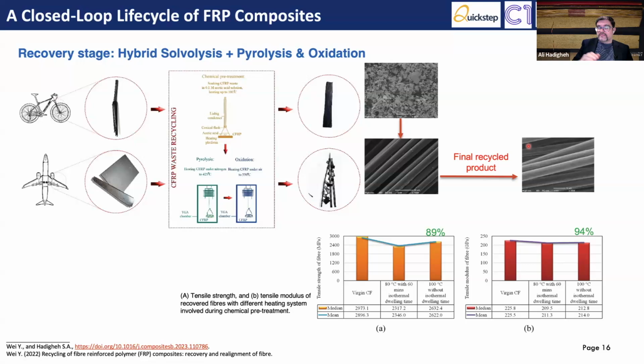Basically, we use solvolysis as a pre-treatment method for separating fiber from epoxy, and then go through the pyrolysis. What it does is it reduces the energy demand, and reduces the amount of heat that we have to expose our fibers to. So by that process, we could see very good, high quality carbon fiber at the end, and that's shown in the tensile test that we did in terms of tensile strength and tensile modulus, which was around 94% tensile modulus retention. So it was very good performance.